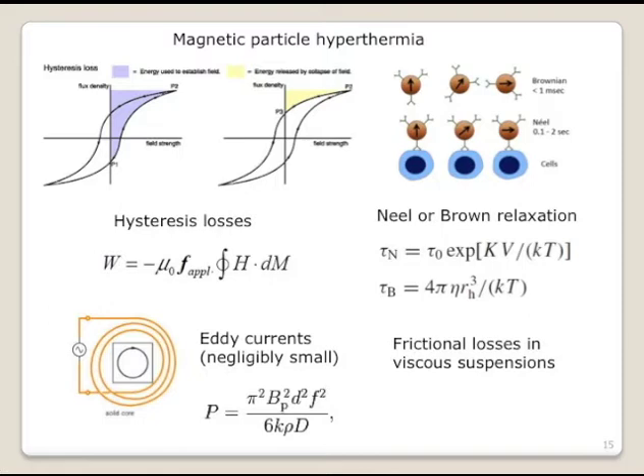The other source is called the Neel and the Brown relaxation. When the magnetic particle size shrinks to the nanoscale, the energy barrier for the magnetic reversal will decrease too. Consequently, this energy is even lower than the thermal energy, like a temperature. They will flip randomly. You do not need to apply the magnetic field. It flips automatically, randomly. This is called Neel relaxation. This can also generate heat, through the momentum change inside the magnetic particle.